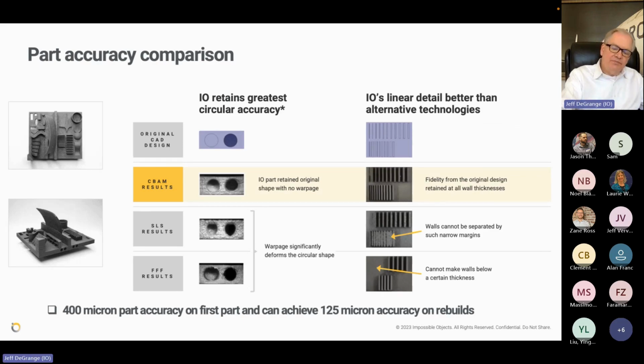As far as part accuracies, on the left side there, we did a number of artifacts, and we've done quite a number of the NIST artifacts, probably hundreds of them. If you look at feature detail compared to more of the installed base additive processes out there, powder bed and extrusion based, you look at the concentricity of holes compared to the CAD design, the CBAM process does pretty good on the left there, as you can see. On the right side of the chart, you'll see feature detail. And with thin walls, there are some factors, but the rule of thumb is we do around 2 millimeter thickness walls with this process, and the fidelity of wall thicknesses that can be built with the CBAM process compared to the incumbent.